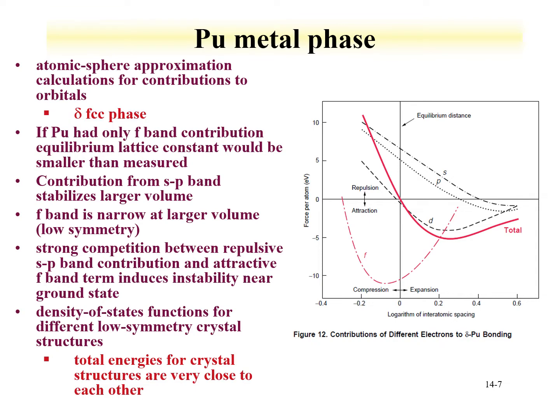If you think about it in terms of a Boltzmann distribution, you can start promoting electrons to higher energy states, from one state to another, so that they can occupy different orbitals, different bonds, different bands, and for the plutonium metal, that's going to manifest itself in different crystal structures.